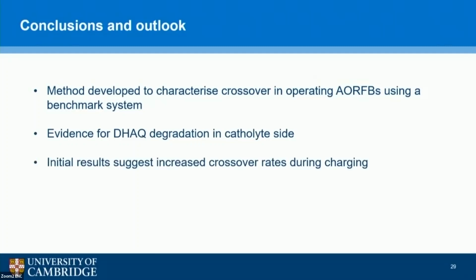And then we've also seen from the initial results that there is a relationship between the charging protocol and the crossover rates. I think this is really interesting because it means that there is the potential to manage the protocol used for charging the battery, and therefore potentially manage the capacity fade that we see.